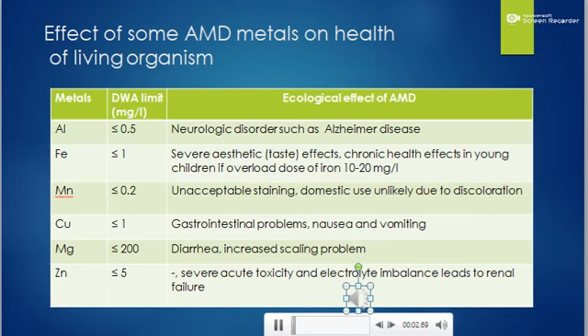This is the effect of some acid-mine drainage metal on the health of the living organism. As aluminium level, if exceeds 0.5 milligram per liter, it causes neurological disorders such as Alzheimer's disease. Iron level, if exceeds 1 milligram per liter, several aesthetic effects, chronic health effects in young children if overdose of iron 10 to 20 milligram per liter. Similarly, manganese cause unacceptable staining, domestic use, unlikely due to discoloration. Copper cause gastrointestinal problem, nausea and vomiting. Magnesium cause diarrhea, increased scaling problem, and zinc cause severe acute toxicity and electrolyte imbalance that leads to renal failure.